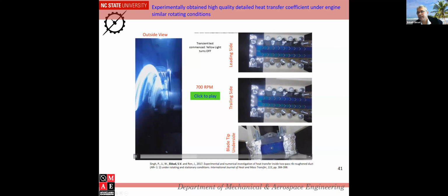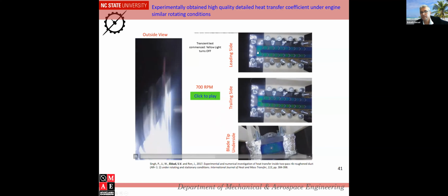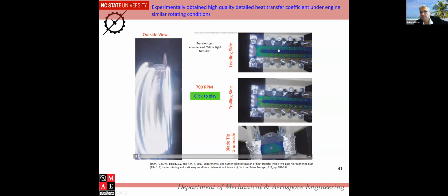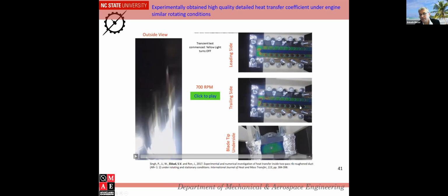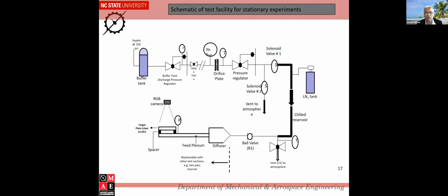You see that these three are rotating right now. You can see the color changes occurring. So what you're seeing is basically the color changes occur. So this area where the color change occurred faster is typically the higher heat transfer coefficient. And as the flow turns around, actually flow comes in this way and it goes through this, the lower heat transfer is on the first pass. The second pass actually is higher heat transfer. And you can see some changes in the color here. So we can convert this into heat transfer and get heat transfer data. So that's the rotation. For stationary, of course, it's easier. All we do is send it through a plexiglass rig and make the same measurements.